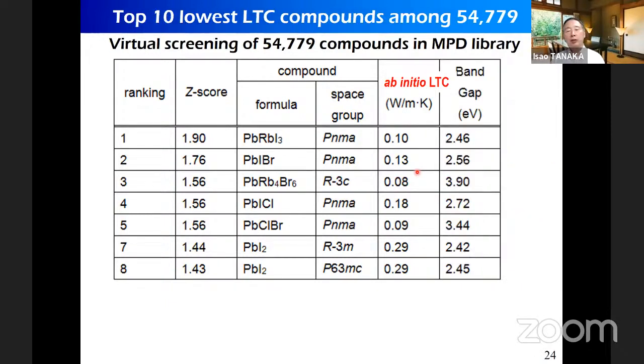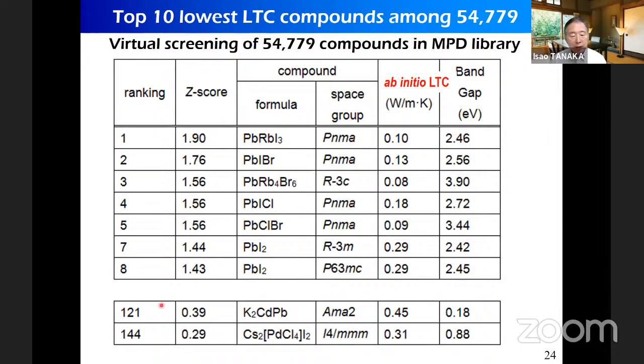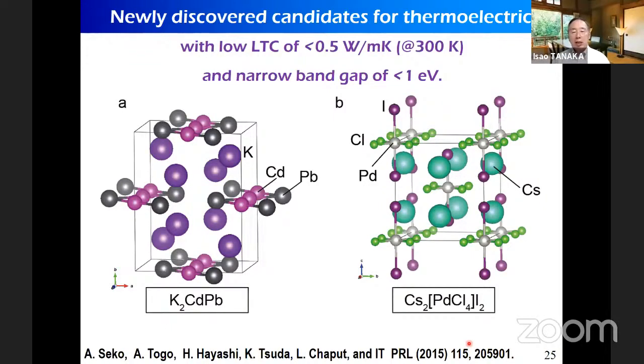And also, if you are interested in thermoelectric applications, then we want to have a material with a narrow band gap. But unfortunately, all these materials show quite a wide band gap by DFT calculation. So those are insulators. But if you look down the whole list at number 121 or number 144, you can find this type of compound which has reasonably low thermal conductivity with quite a narrow band gap. So in this way, using machine learning technique and virtual screening, with the aid of a first principles data set, we were able to discover this type of compound as a candidate for thermoelectrics.